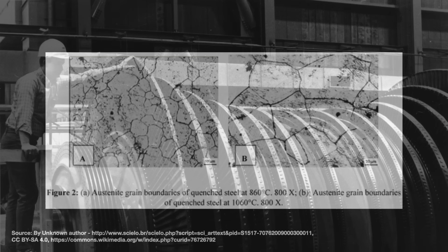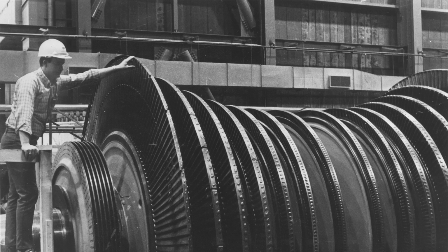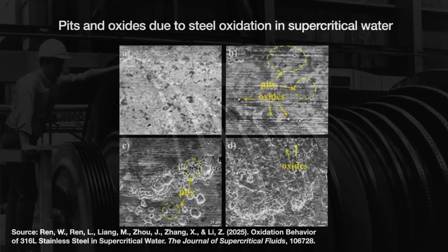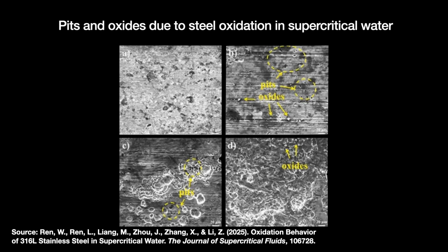First, these austenitic steels expand a lot in high heat while also poorly transferring that heat. So when the turbines start up and shut down, their thick-walled components will have hotter outsides but cooler insides. The hotter areas expand more than the cooler inner areas, thus leading to cracking. Second was oxidation. Superheated steam can oxidize the steel, creating oxides on its surface that eventually flake off. These flakes then either build up in the boiler tubes, blocking their flows, or chip away at the turbine's insides, breaking them. These were complicated problems.